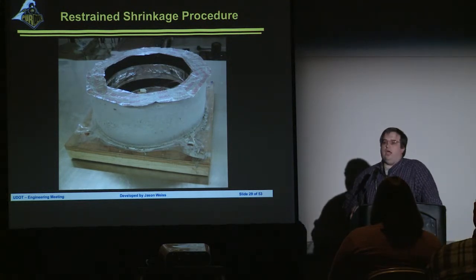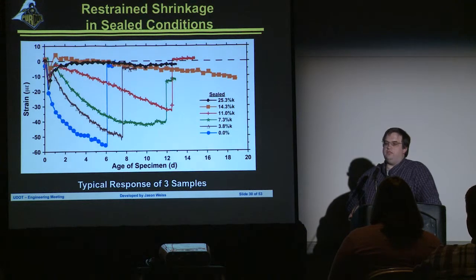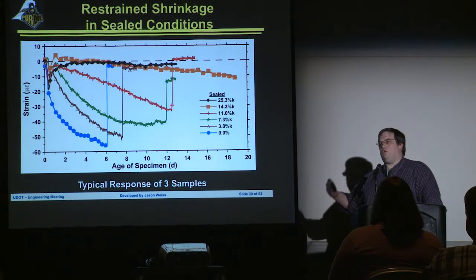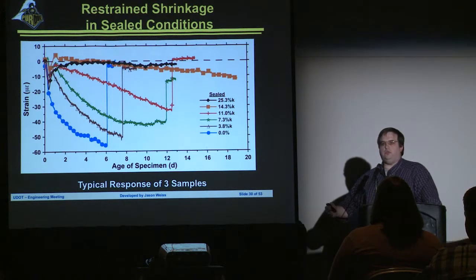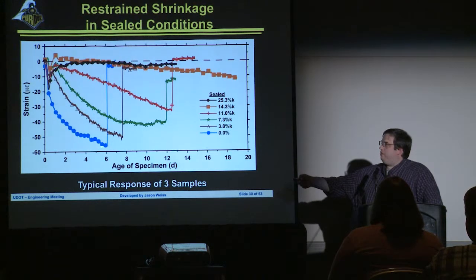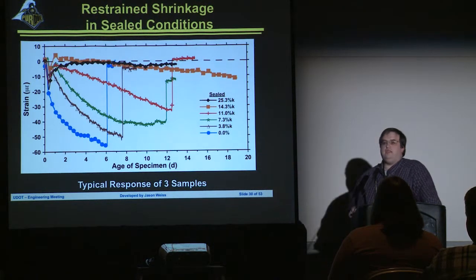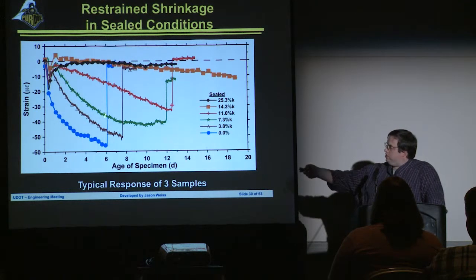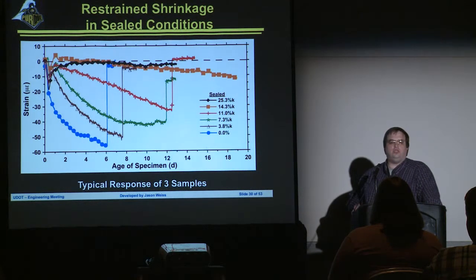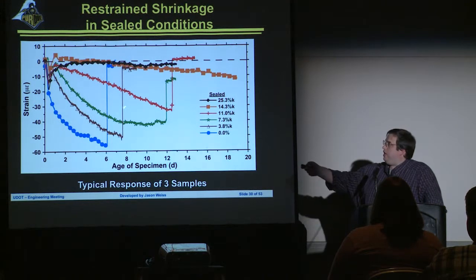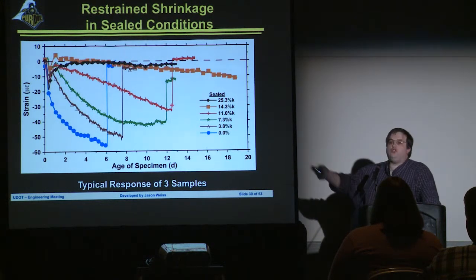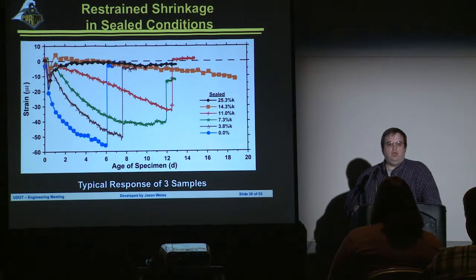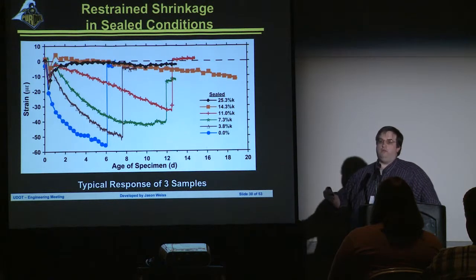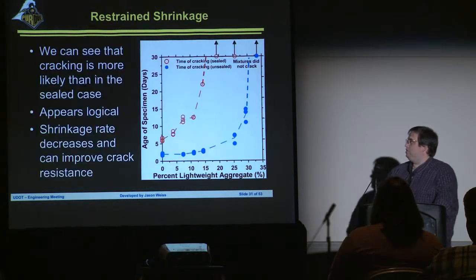We can actually do that, and we can start to look at the strains that develop inside of the system. And I will mention that there are equations out there that directly relate the strain that's measured inside of the ring with the stresses that develop inside of the concrete. Our blue, again, is our plain system. Sealed, after 6 days, the system cracks. This big jump here is the release of stress in the system, which occurs because of a crack. As we add more and more lightweight aggregate, we see almost no stress developing in the system. This means that we have more capacity inside of the system for loading, for thermal changes, for other things happening before the system would start to crack.